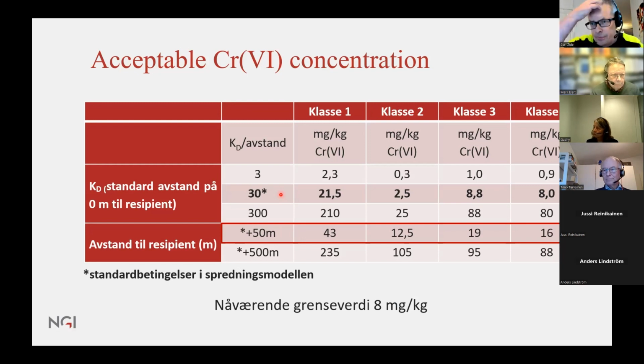Very much so. For example, we also did calculations with values from our laboratory tests, and there we got up to 2,000, 3,000 liters per kilogram. That's what I found as well. And that was one of the reasons the authorities were relieved that field tests and laboratory tests show quite different values here. So also in this case, the KD value of 300 would be conservative.